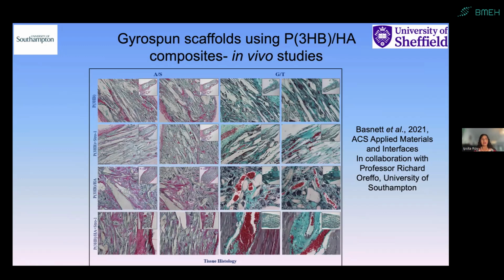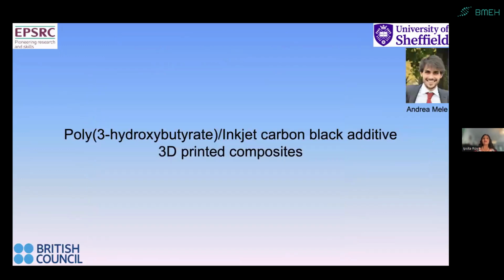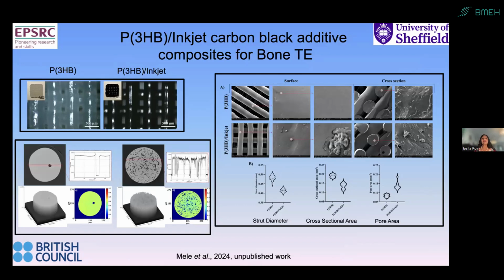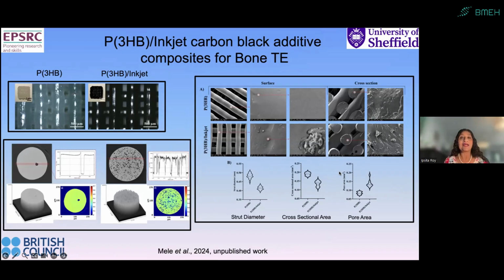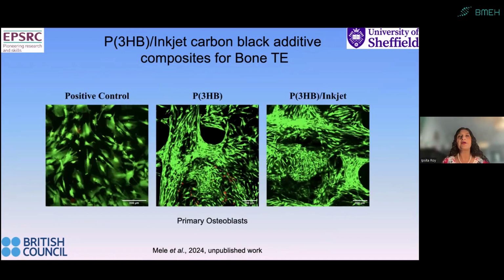We've also done recently some work with inkjet carbon black additive, which we added to poly-3-hydroxybutyrate. This was work done by Dr. Andrea Mele from my lab. And you can see that he managed to 3D print them beautifully with high fidelity. And in the presence of the inkjet carbon black additive, we got high porosity, as you can see from the micro-CT image here, and also the fidelity of printing was enhanced. So this was also found to be very, very biocompatible.